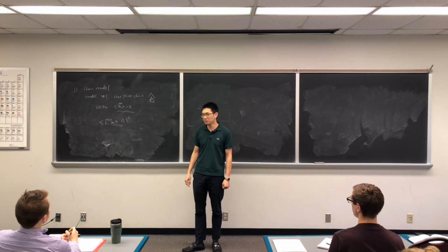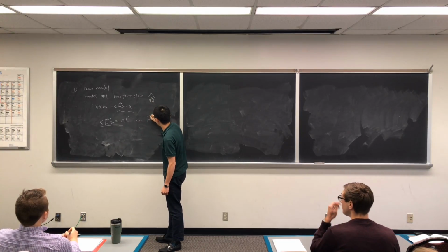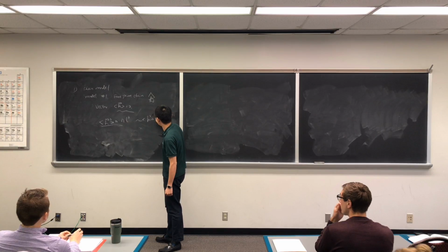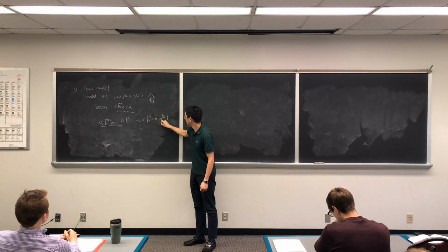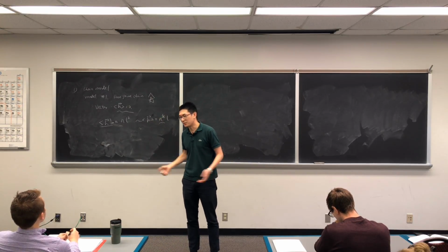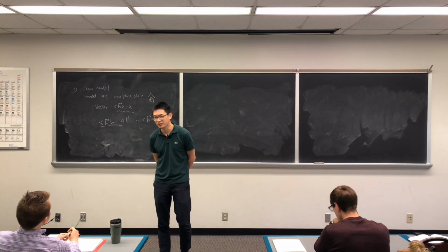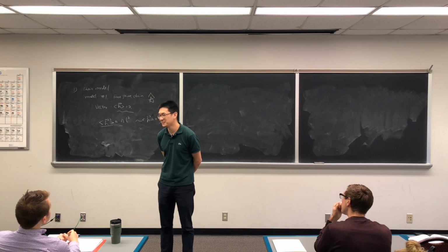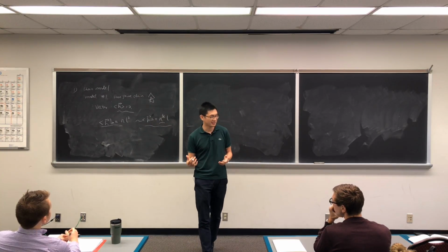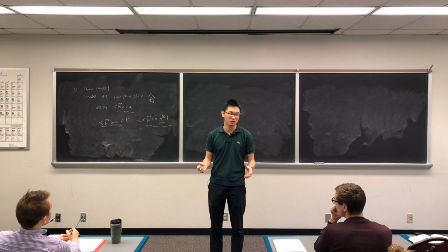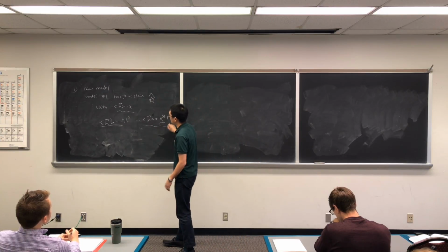The take-home message is that this end-to-end distance would be N to the half times L. So it's not a linear scale with the number of chain bonds, right? That's how we understand this part. And we chatted a little bit about a more complicated way to use matrices to understand the self-term versus non-self-term. That's the beauty of this part.